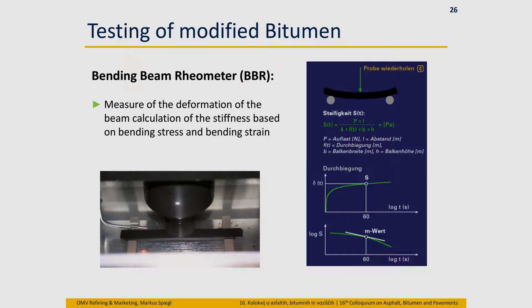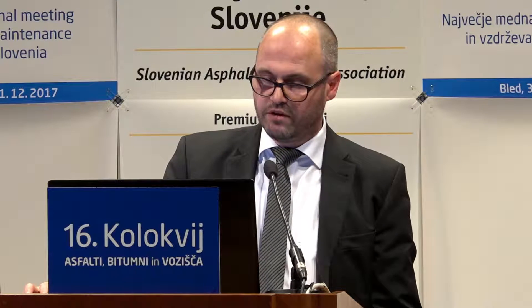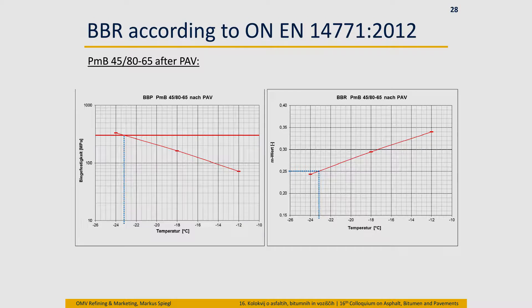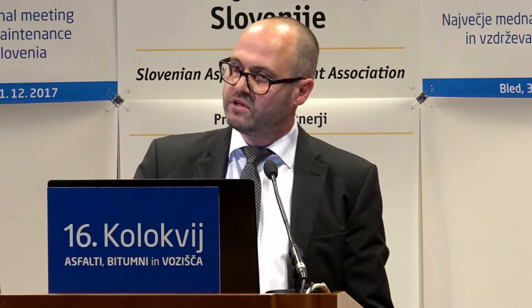BBR testing — I think everybody is familiar with this. Again, only the test results. For paving-grade bitumen, the stiffness threshold value at 300 MPa is at minus 19°C. For a normal PMB we have here around minus 23°C. And if you would go to the high-modified PMB, we end up with minus 25°C. So even here you see an improvement of the highly modified PMB. Not everywhere is it necessary to have this improvement, but with this modification you automatically gain a further benefit.